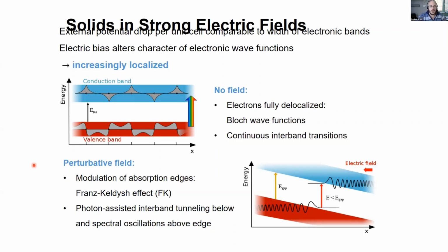So we can see the system as a standard semiconductor, with valence and conduction band. What happens when you apply an electric field? That can be optical, as in this case. The non-resonant excitation of the material is like an electrical bias on the semiconductor. So we bias the system. That means that we bend in real space the band structure of the semiconductor, and we can have the so-called Franz-Keldysh effect. So we can have absorption below gap.